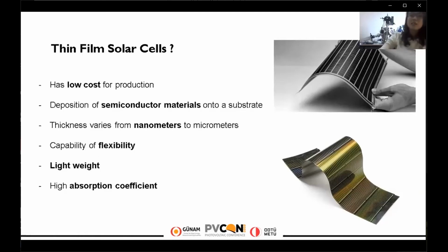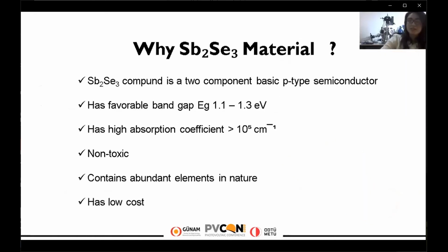And crystalline silicon solar cells need a very thick layer to absorb the incident sunlight, but thin film solar cells have a very high absorption coefficient, and these are the advantages over crystalline silicon solar cells. And why antimony selenide instead of the other commercially used materials, CIGS, cadmium telluride, CZTS, which are more popular?